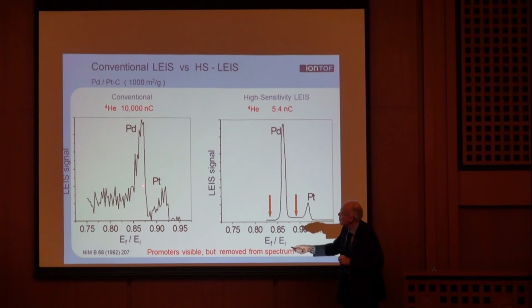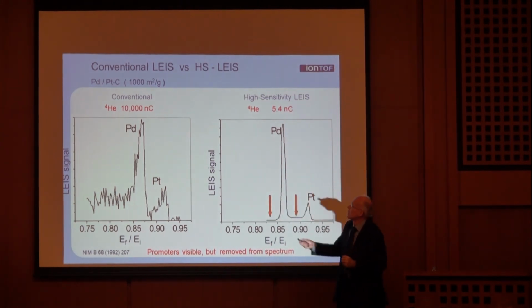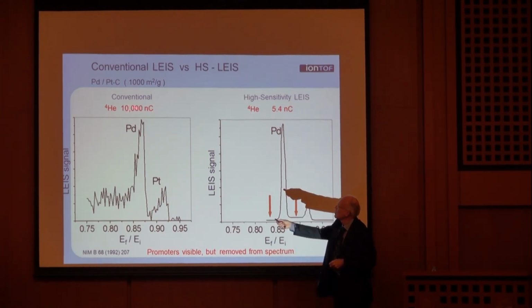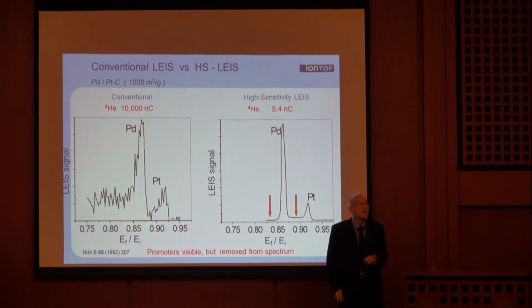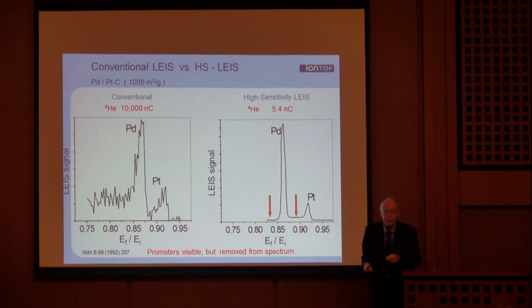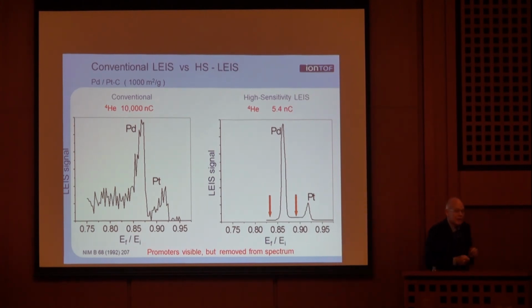Well, in the old days, we could see palladium, we could see platinum. However, the number of ions that I needed to get this spectrum was a lot. 10,000 nanocoulomb, which means actually I kill the surface before I get my spectrum. However, we developed a new instrument, and there you see the new instrument. Instead of 10,000, I need about 5 nanocoulomb. So very much less ions. And at the same time, you see this looks much nicer.